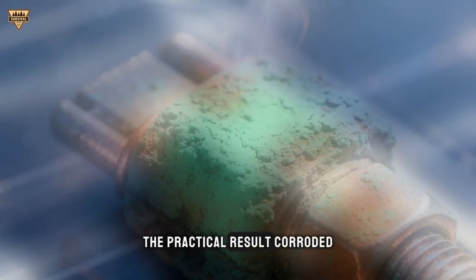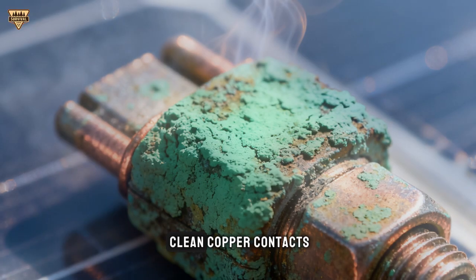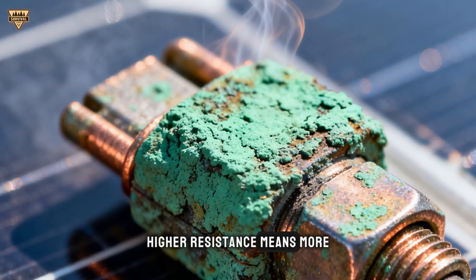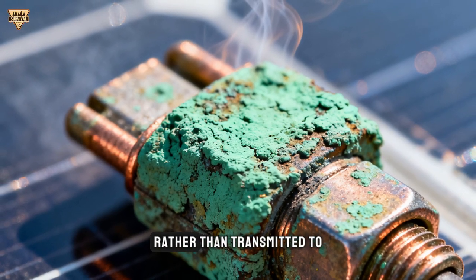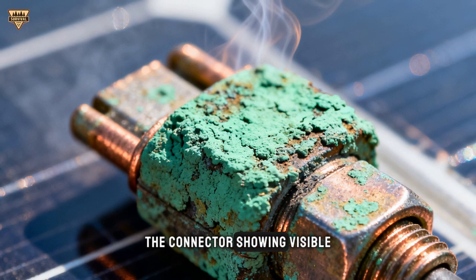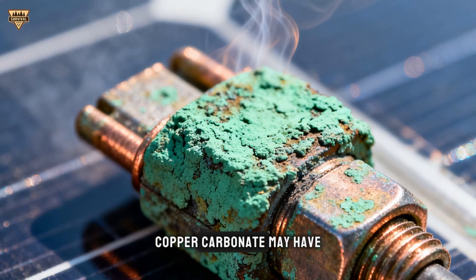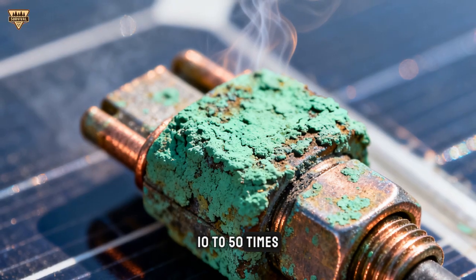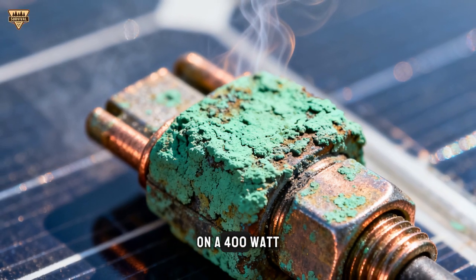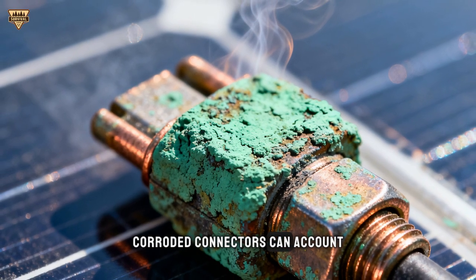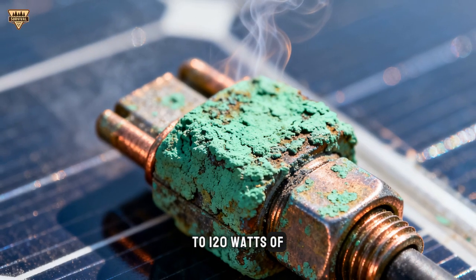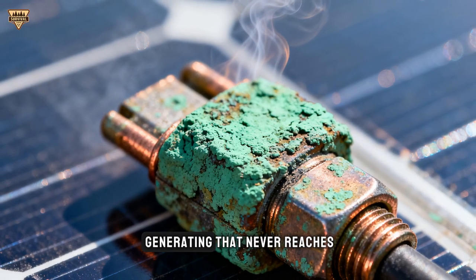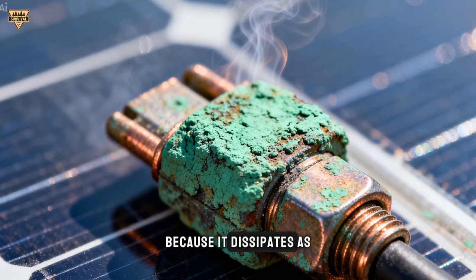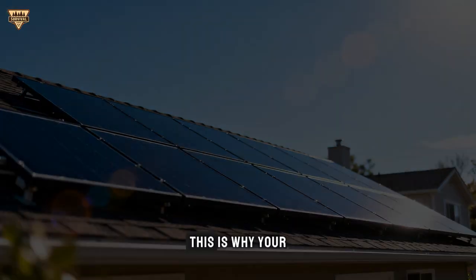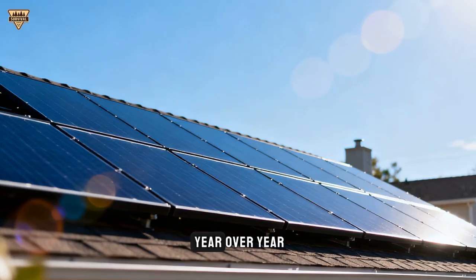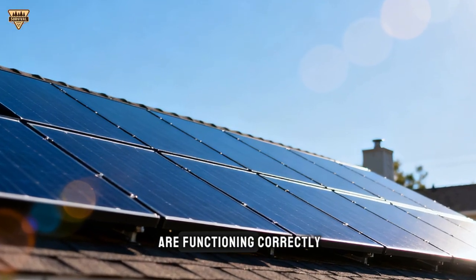The practical result: corroded connector contacts have higher resistance than clean copper contacts. Higher resistance means more energy is lost as heat at the connector rather than transmitted to your battery. A connector showing visible green oxidation, copper carbonate, may have contact resistance 10 to 50 times higher than a clean connector. On a 400-watt panel system, corroded connectors can account for 60 to 120 watts of invisible power loss. Energy your panels are generating that never reaches your battery because it dissipates as heat at a corroded contact point. This is why your solar system's output drops year over year, even when panels themselves are functioning correctly.